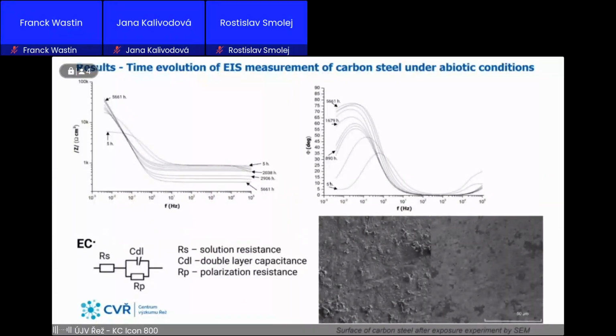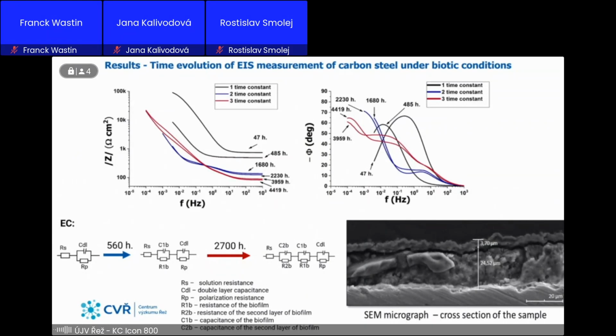And you can see that the shift of time constant is slowly down to lower frequencies. This means that the corrosion is slowed down, and we don't observe a second time constant that deals with the oxide layer, so the corrosion was in active state without protection oxide layer. On the contrary, in biotic environment, we observe time evolution of 3 time constants. The second time constant was observed after 560 hours, and the third time constant was observed after 2,700 hours.